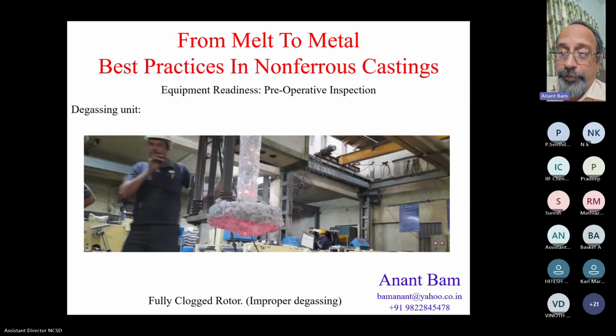This is a photograph of the dirtiest rotor I have ever seen. I have to tell you that this is a rotor. The white thing which you find, inverted T-shaped, is the rotor of the degassing machine. And I cannot see any fin or any rib. All I can see is just oxide, oxide, and oxide, thoroughly deposited for ages. Naturally, the whole of the shaft is also clogged. Nitrogen or argon is not coming out. This thing is not able to churn. And hence, degassing is just for show.